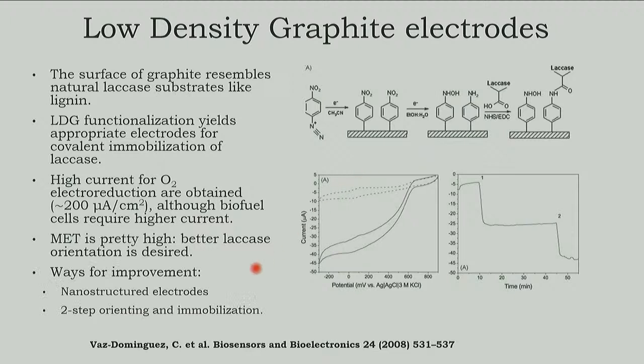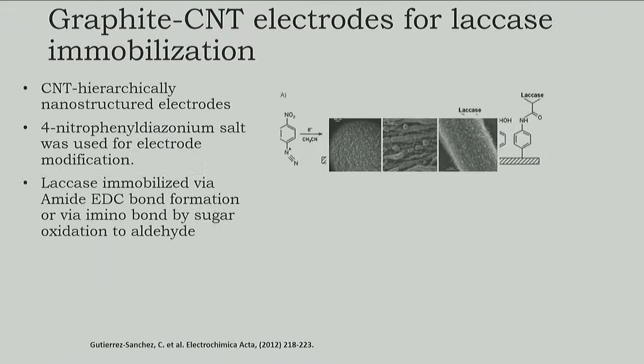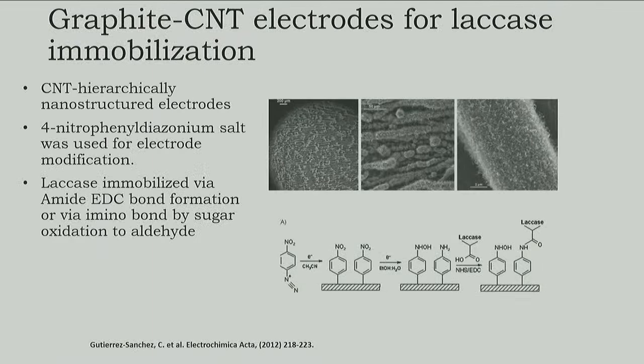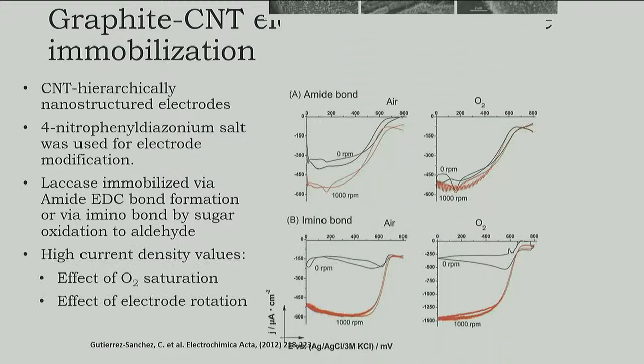How to improve it? Well, we can use nanostructured electrodes and immobilization strategies that take 2 steps. First, to make an orientation by affinity, and later catch it with covalent bonding. So how does this work with nanostructured electrodes? We used, in this case, carbon nanotubes that are hierarchically nanostructured. It means that they're fibers of micro size, and nanotubes are grown on the surface of these fibers, giving this kind of hairy electrode, very conductive with a very big area, and we make exactly the same kind of reactions. Okay, so in this case we made an amide bond, and this is what we get.